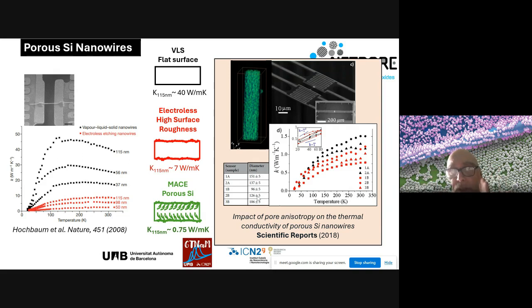So there are some dimensions, but what is nice is that with the nanosphere lithography and metal-assisted etching, you can play with the dimensions. So you can have also nanospheres of 2 microns, for example. So we wanted to be close to the phonon confinement, so with 100 nanometer diameter. But in principle, you can do arrays of pillars of 500 nanometers, 1 micron, and for other kind of application, I think the bio, for example, it's possible to plan different structures with a different mechanical stability.